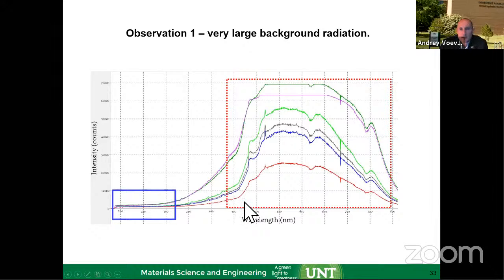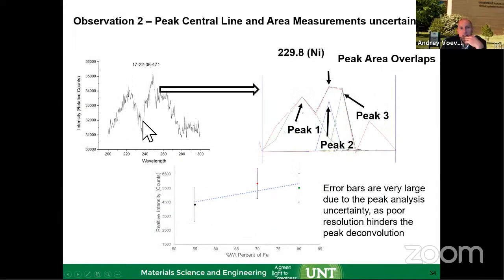And what we found is that the region of visible light to infrared is very highly dynamic and very hard for us to focus on. It goes sometimes off the chart, sometimes goes down, during the process itself. So it goes up and down in intensity very rapidly as it hits or does not hit different powders in the laser beam. So we're then looking at a UV region, which seems to be a little less affected by that blackbody radiation, which we see more in the infrared. So in the UV region, we can start seeing some individual peaks and structures.